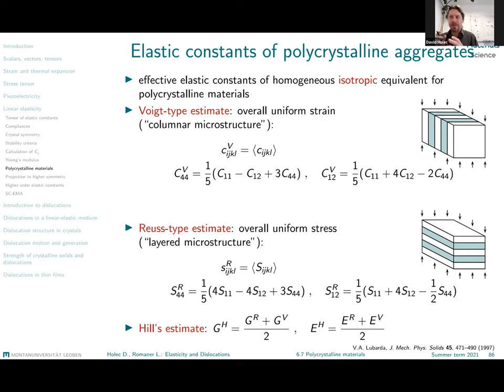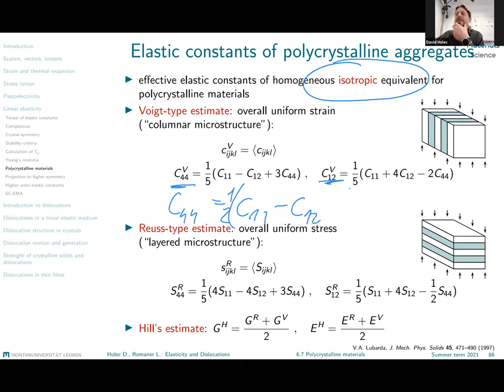And a second note, this may not be so clear from what I have said here: the point that we have all orientations present with the same probability leads to an ensemble which will have a macroscopically isotropic elastic response. That means I will eventually describe my material using only two elastic constants. The third one can be calculated out of those, right? We know that this is (C11 minus C12)/2. The same thing for the Reuss. Again, it is an elastically isotropic aggregate of grains. So then I indeed end up with only two elastic constants.